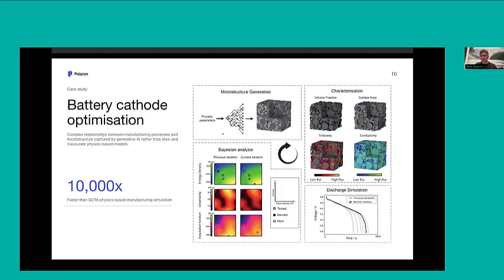The final step is, can we connect this image data that we know is linked to the process back to the performance of our material, and then optimize to identify the best process parameters that give us the best structure, that give us the best performance. And we have developed a methodology that uses this 2D to 3D reconstruction algorithm as part of a way of learning the relationship between process and structure.